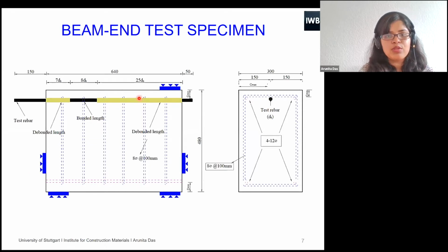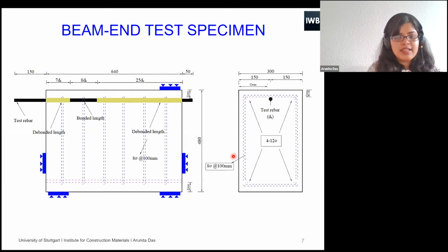So the restraints which I am talking about are those during the pull-out after fire. This restraint is provided in order to prevent uplift of the specimen. These restraints are provided to prevent the specimen from sliding, and these restraints are provided to keep the specimen in position. But all the restraints are provided sufficiently far from the bonded length so that there will be no effect of these restraints on the bonded length.